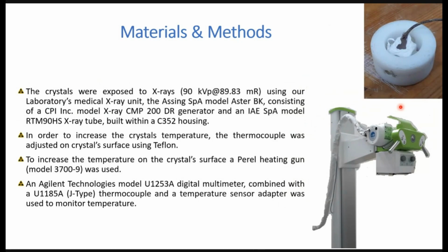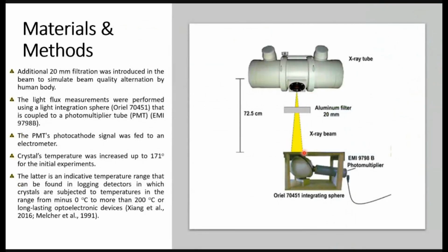A thermocouple is attached every time to the crystal surface in order to monitor the temperature on the crystal surface, and then the sample is placed in the input port of an integrating sphere. All samples are irradiated with an X-ray tube. The beam of the tube is filtered by a 2-centimeter aluminum filter in order to simulate the beam hardening by the human chest. Afterwards, the signal produced by the crystal is fed to a photomultiplier tube, to the photocathode.